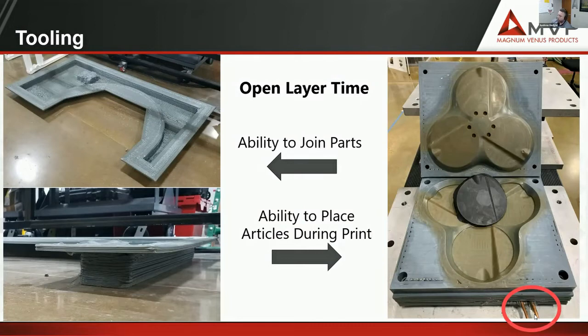And then this was a pre-preg material that was used on the compression mold, and it was used for some gas caps. But you can see there was no release agent or sealer put on. It was printed, milled, and then ready for production. So it's pretty cool seeing that mold. We showcased it at the CAMX show this past year. We have it at the facility here, but it's just showing you what you could do in the different processes of vacuum infusion, compression molding, thermoforming, whatever it is, you could use this tooling for many different types of processes.